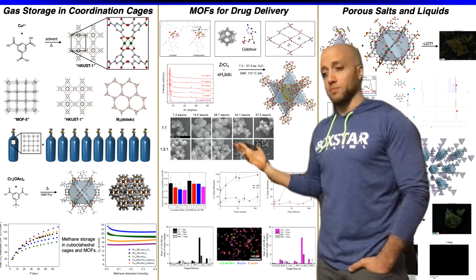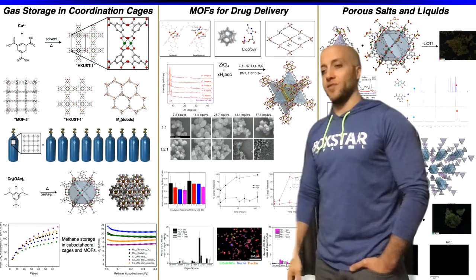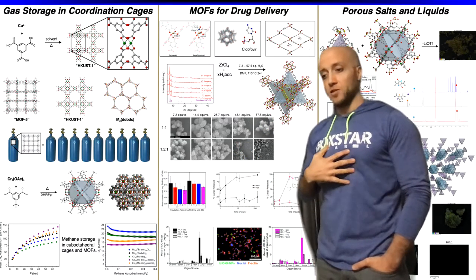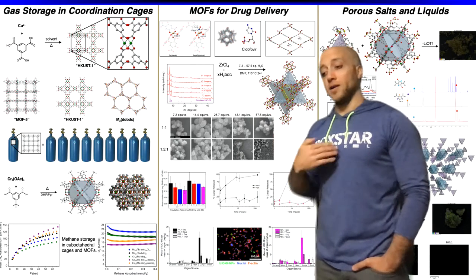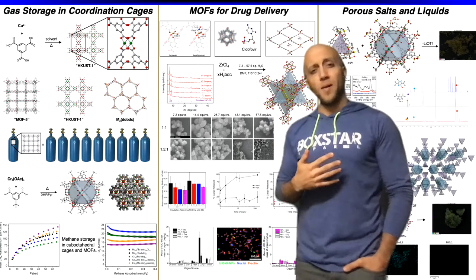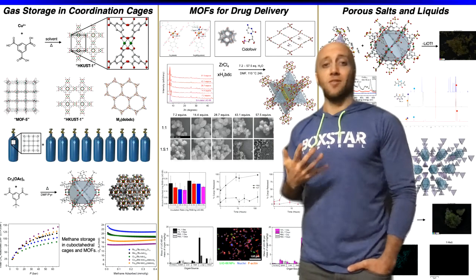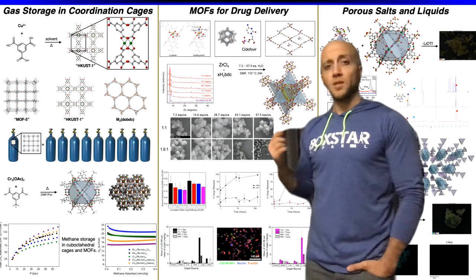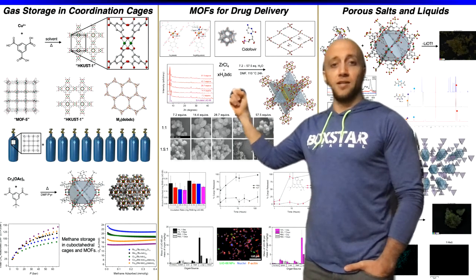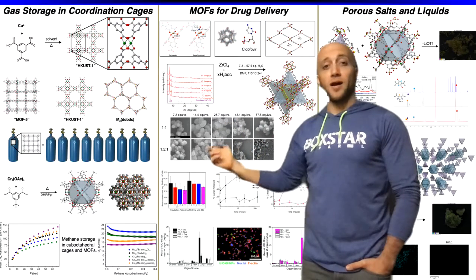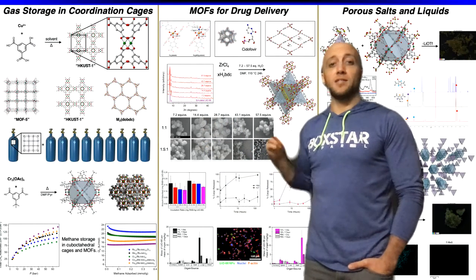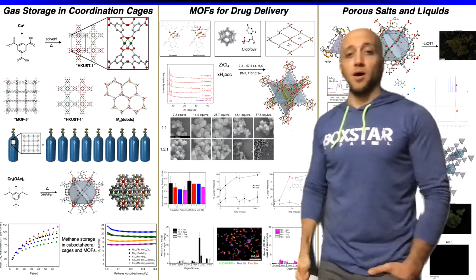It's a zirconium-based MOF, and the important thing is if you want to deliver a drug to the pulmonary space, you need to be able to tune particle size, because where in your lungs these particles are delivered is largely governed by the size of the particles that you inhale. So here we can tune reaction conditions, including the metal to organic linker ratio and water content, and very precisely tune the particle size of these MOFs.